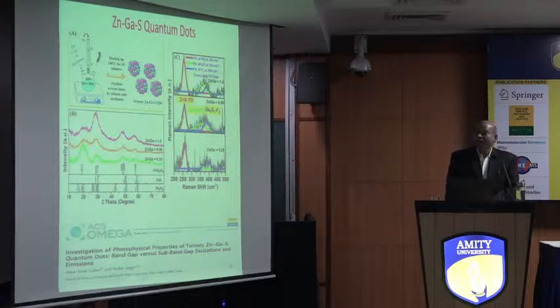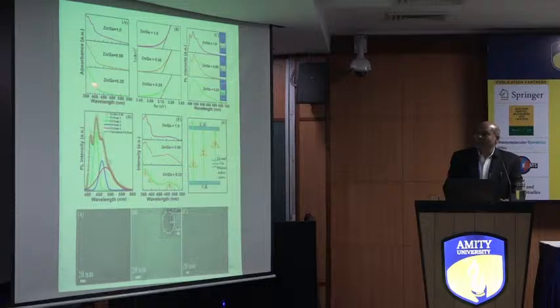This is the ternary quantum dot. We prepared it by a very simple method. Then what we do is we change the zinc and gallium ratio here. Then we take the absorption spectra, which is showing some quantum dot behavior. Then we calculate the band gap, which comes to about 3.15 electron volt. This is the PL spectra, showing different peaks coming here. If different peaks are coming, this is showing some different states. The size is about 3 nanometer.